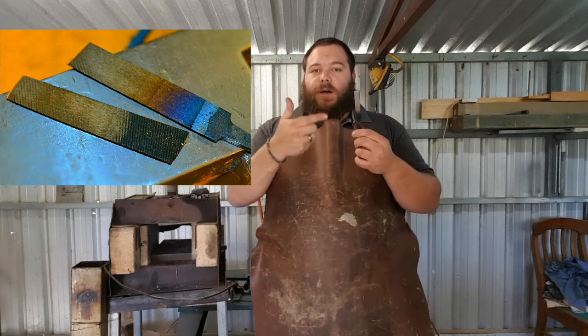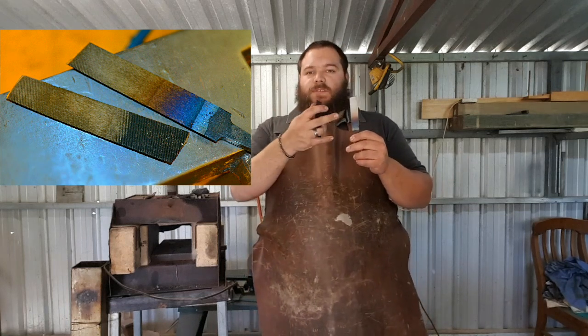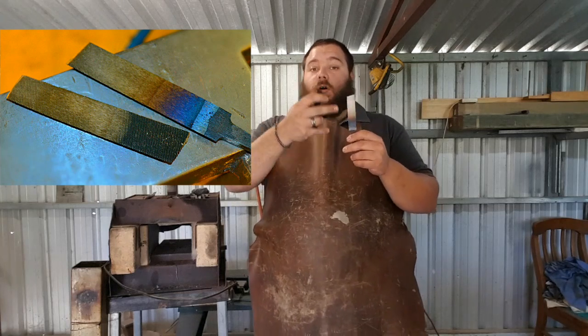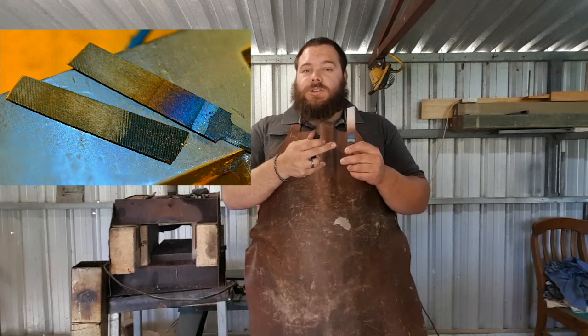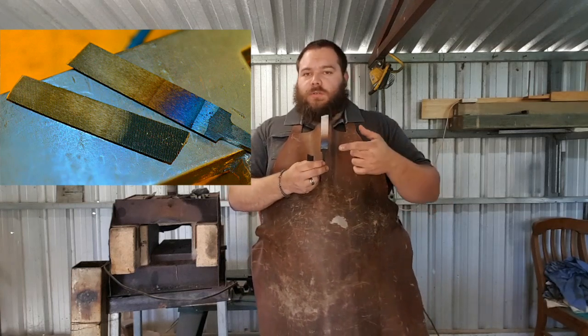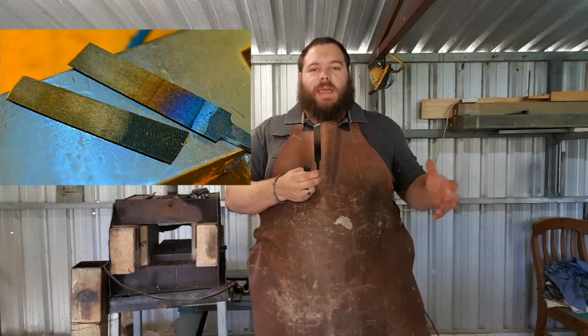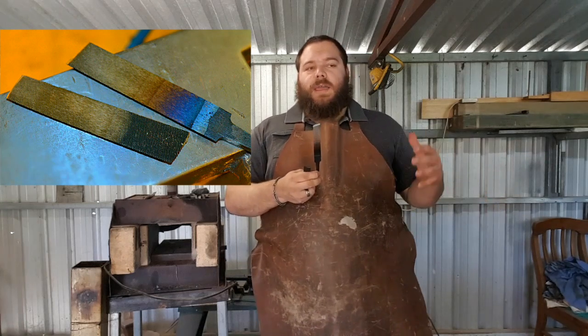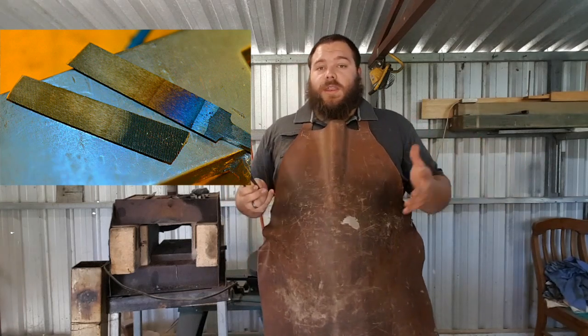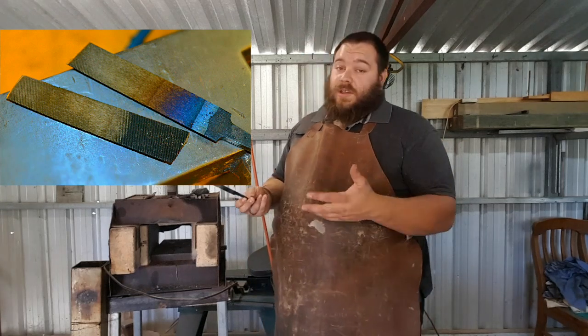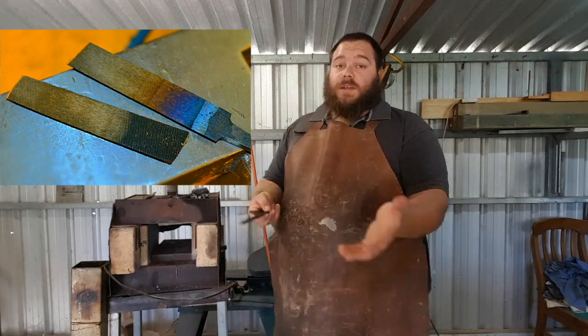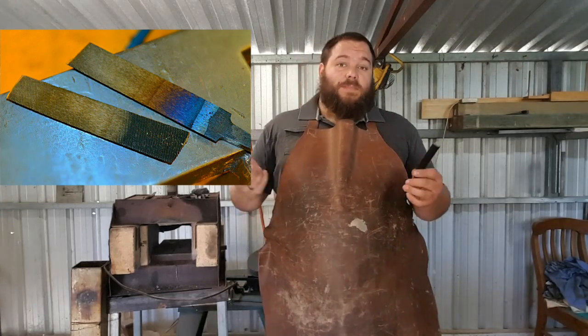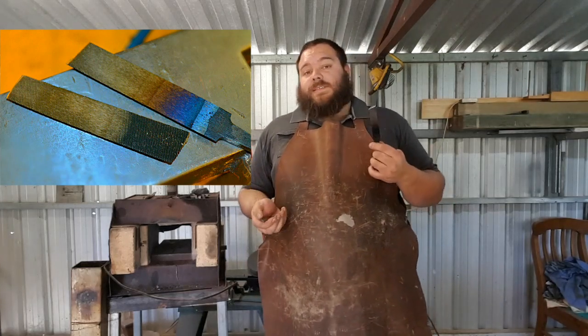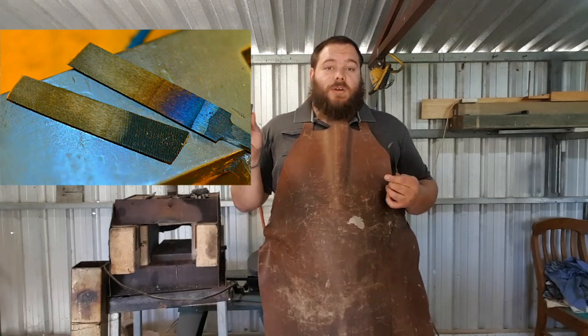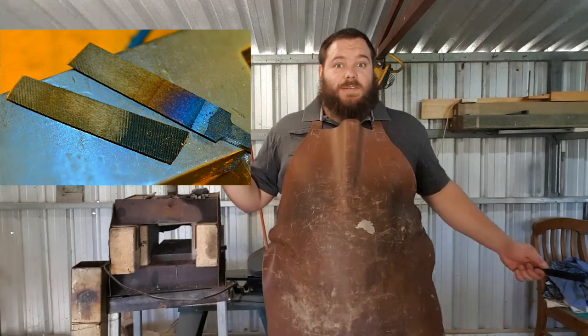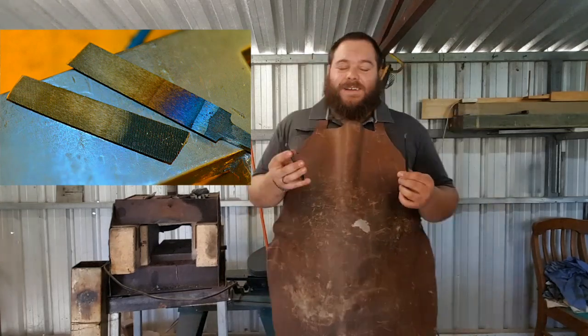far more variable, but that's on purpose. But it also demonstrates how easy it is to overshoot the temperature when using a torch temper or forge temper. And if you overshoot the temperature, then you've softened the blade or the cutting tool, whatever you're trying to make, too far, and therefore are not going to get the edge retention that you would get otherwise, and so you're going to have to reheat treat, which means re-quench, re-temper, and renormalize before quenching. And that can be a massive pain in the butt, whereas with the oven temper you don't have that risk. You throw it in the oven, you leave it there, it's done, and that's spectacular.